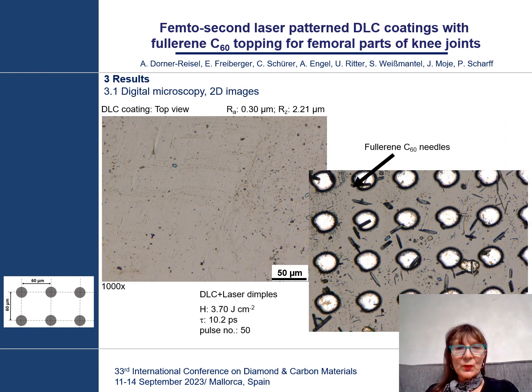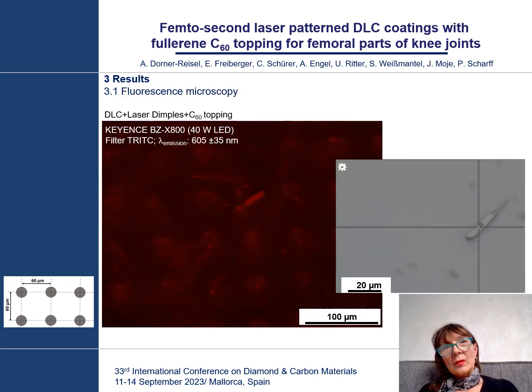Now you can see top views of the DLC as deposited on the left hand. And on the right hand, there is a micrograph of the DLC with the laser patterning and the C60 needle-like crystals. By the way, the C60 needles also show a minor fluorescence effect. This seems to be especially advantageous in medical applications if you would like to track nanomaterials like the C60 molecules.